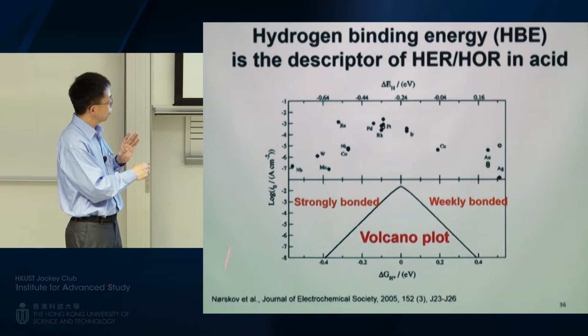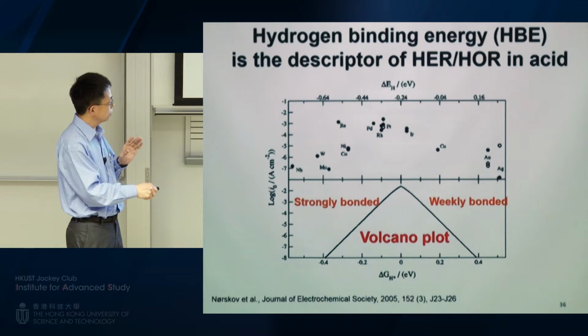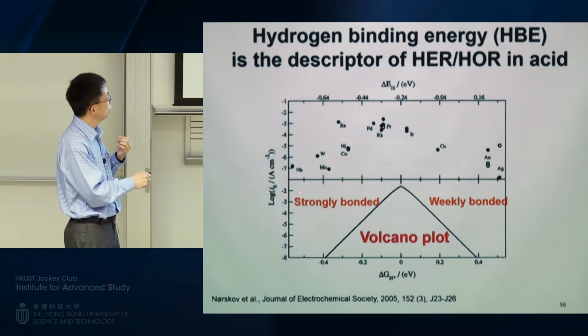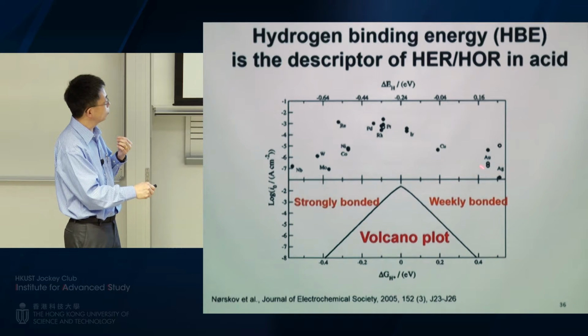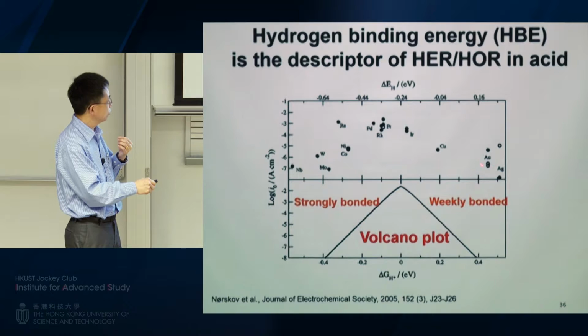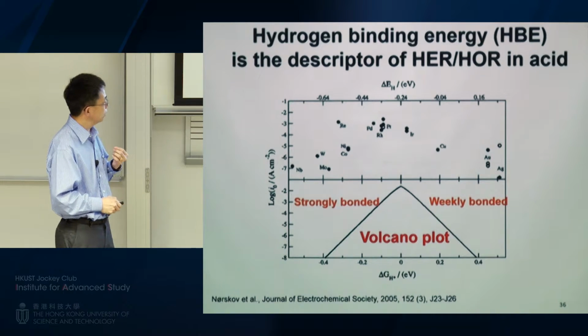So for this particular paper, the horizontal axis is a DFT calculation. The vertical axis is the experimentally measured reactivity. And you can see all the metals here. Indeed, we have a volcano plot. So you can see platinum is sitting at the best place. And gold and silver are very bad because they don't adsorb hydrogen as strongly as needed.